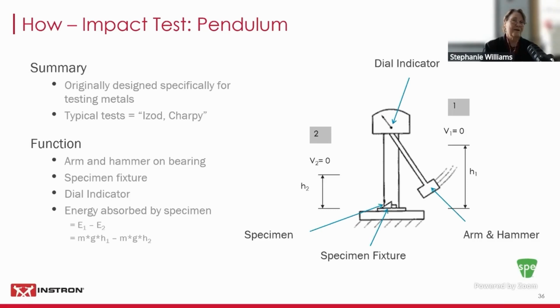Simply put, we raise the mass up to the latch position, which is noted as position 1 in the diagram. When we release that mass, it swings down and through the sample, impacts the sample, and then goes up to another angle, lower than the first, of course. So we have 2 energy markers: the energy we started with at 1, and the energy we got to at 2. We simply do the math. Latched energy minus the second energy is, theoretically, the energy absorbed by the specimen.